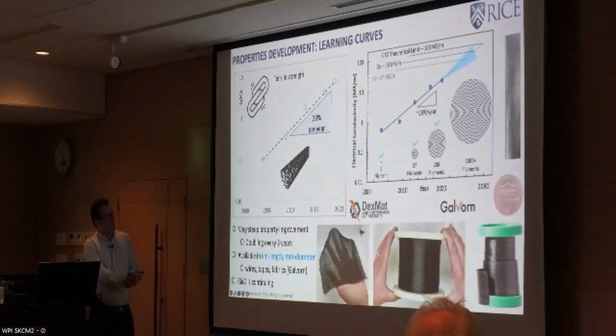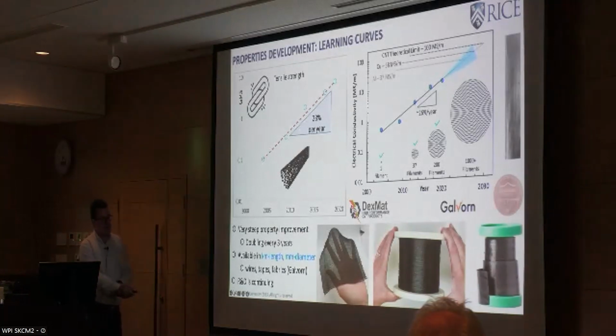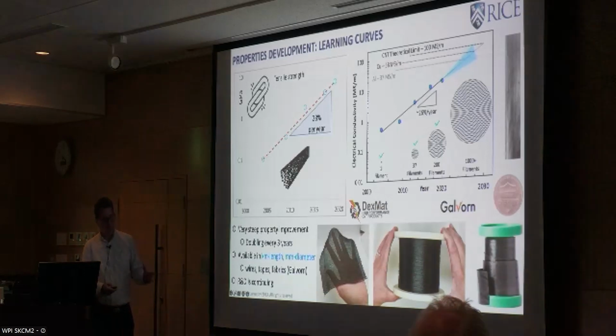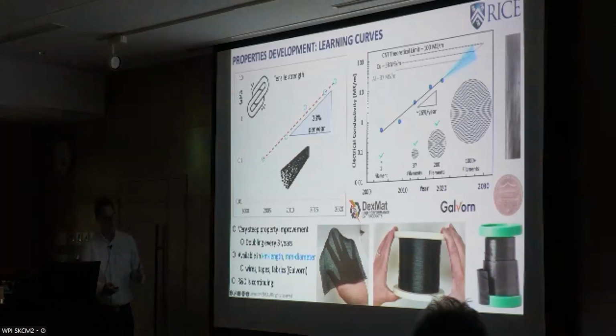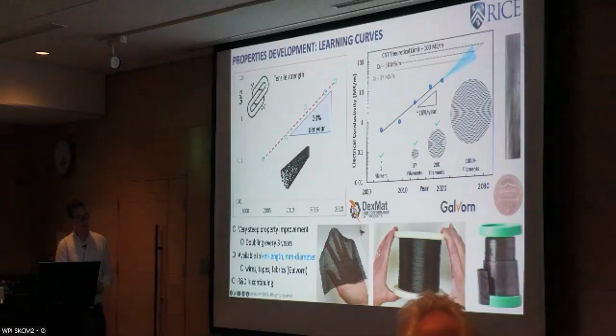Now, when we started making fibers in 2004 with Rick Smalley, we were very excited with a paper in Science for this, but the properties were terrible. There's about 100 megapascal strength and about half a million Siemens per meter electrical conductivity. But then it turns out that by understanding processing, understanding phase behavior, and understanding the relationship between the properties of the nanotubes and the properties of the fibers, we were able to improve conductivity essentially doubling every 3 years. And the samples got bigger and bigger.